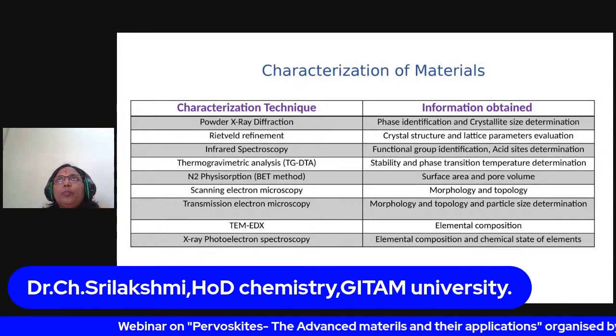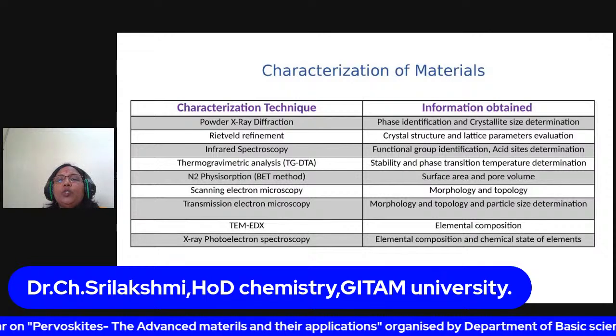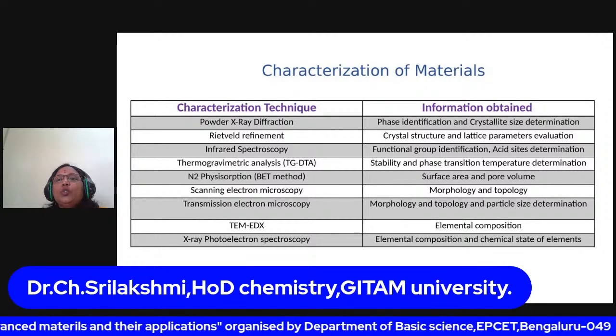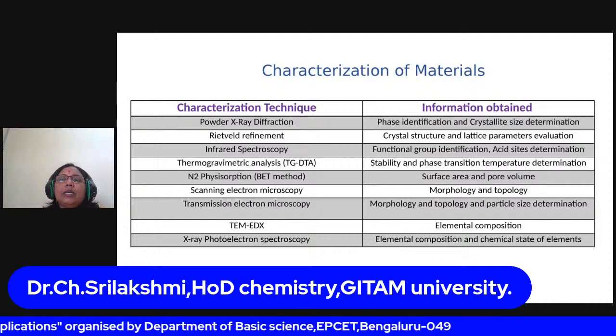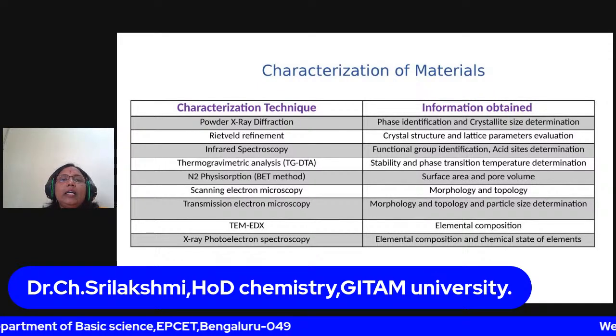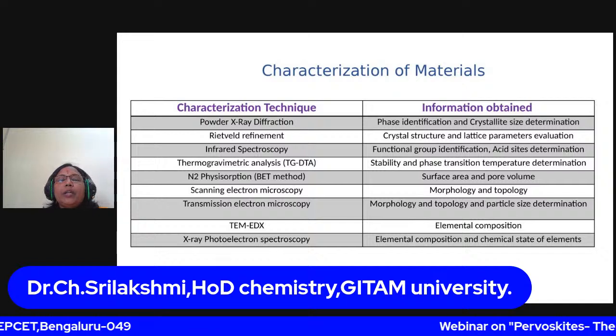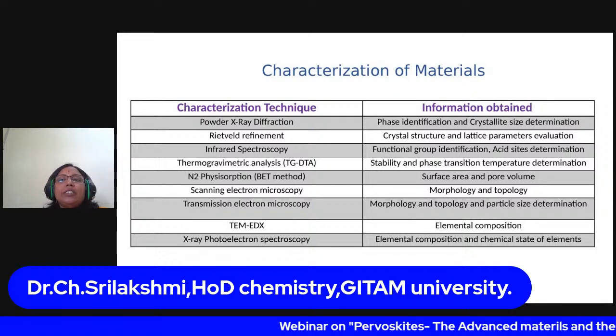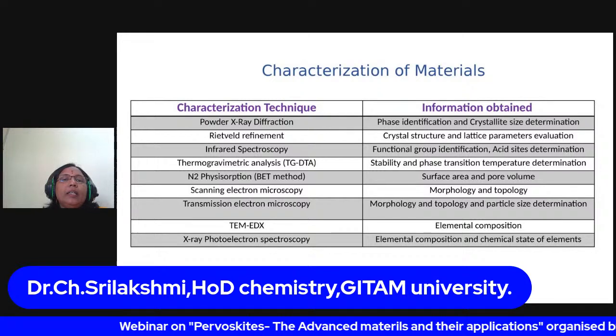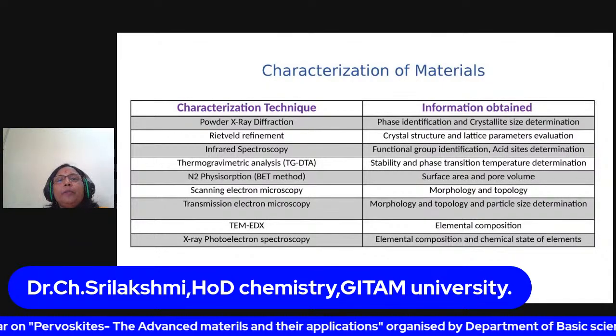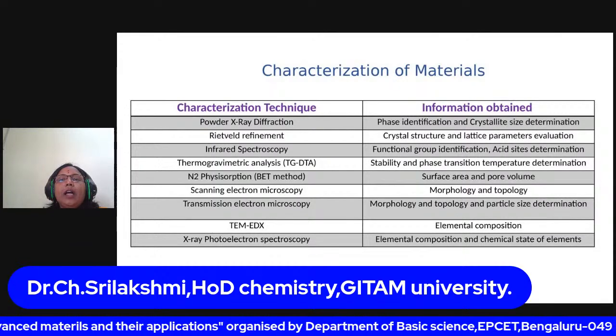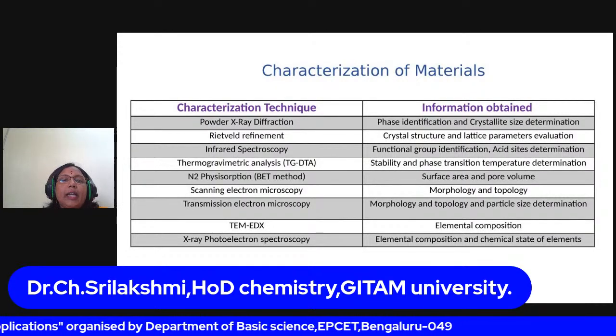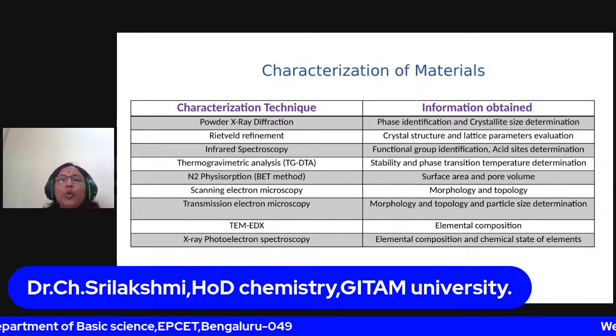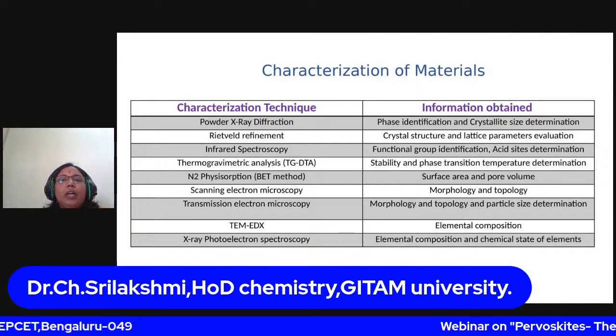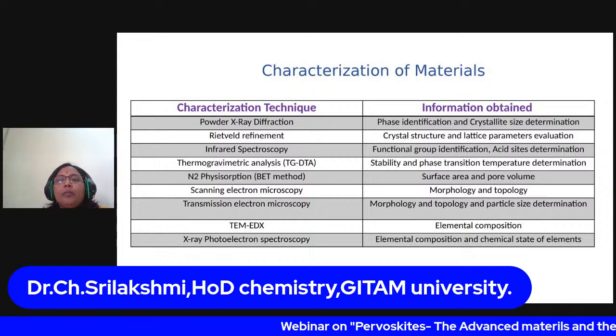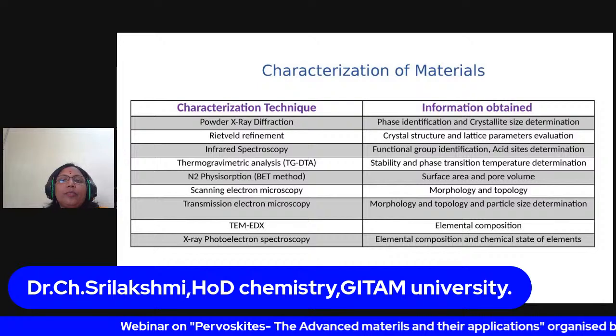I use infrared spectroscopy to identify the functional groups and also to determine the type of acid sites present in the sample. TGA, thermogravimetric analysis, gives information about the stability, and the phase transition temperature can also be obtained. N2 physisorption by the BET method is mainly to obtain the surface area and pore volume of the materials, and SEM, scanning electron microscopy, is for the morphology and topology of the sample. TEM serves the same purpose, but here we can also determine the particle size of our sample.